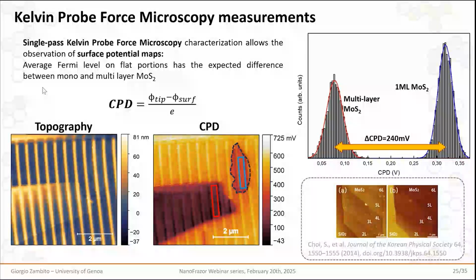Also, I want to stress that this was performed with a single pass configuration, which means that at the same time, pixel by pixel, we are able to measure the topography signal and the CPD signal. So these two maps, for example, are co-localized. The first interesting thing that we notice is that while in the topography signal, the presence of the monolayer is very hard to locate, it's very clear in the CPD image, where we have a very strong contrast between the monolayer and the CPD signal of the PPA. And if we plot a histogram of the CPD values extracted from flat regions of few layer and monolayer flakes, we observe two distributions that are more or less 240 millivolts apart, which is coherent with the intrinsic difference in work function between monolayer and multilayer MoS2.